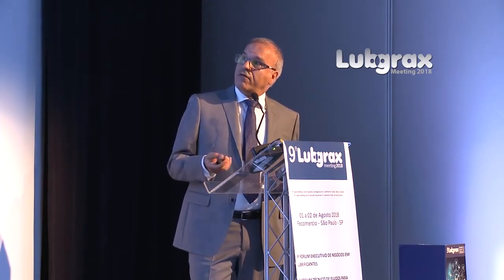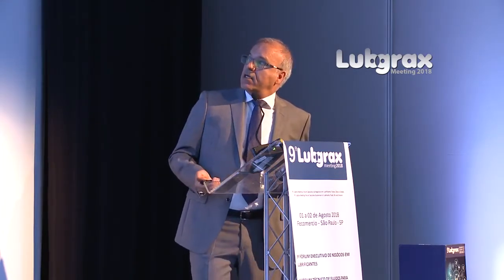T600 outperformed the reference oil in all aspects. The only deviation was on the low temperature mobility. T600 improves both viscosity and solvency of other oils, so very easily can be combined and is compatible with other types of oils, group 1, 2, 3, of course. And last but not least, I went through the increased productivity index, which I really, really sincerely believe is important for the manufacturers. And with those words, obrigado, and thank you very much.